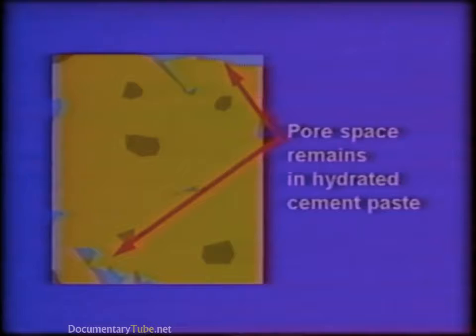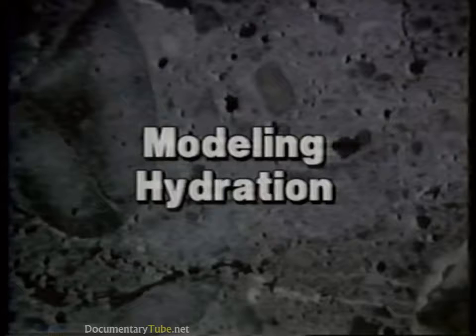Concrete will harden within a few hours, but hydration continues for weeks, even years, after placement. Here is a picture of cement particles before exposure to water. Dry cement is a fine powder, and the particles are not attached to each other. After the cement is mixed with water and allowed to stand, the picture is quite different. Now the particles are grouped together and attached by solid material that provides structural integrity.